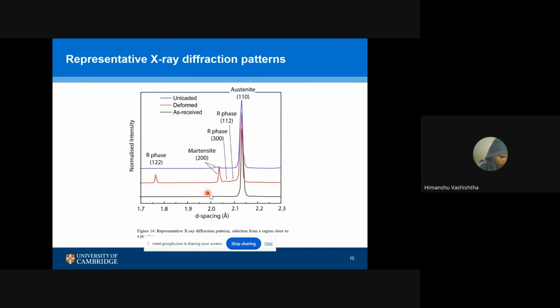As received, that means the as-printed stent, just a B2 cubic phase was there. When we deformed it, several new peaks evolved. Those peaks belong to the R phase, and some peaks belong to the martensitic phase, and some R phase again. When we unloaded it, this peak has gone. A small amount of martensite has been retained, so the recovery was not complete. Perfect recovery was not there; some amount of martensite has been retained in the material even after removing the complete load. This is shown in the blue image.